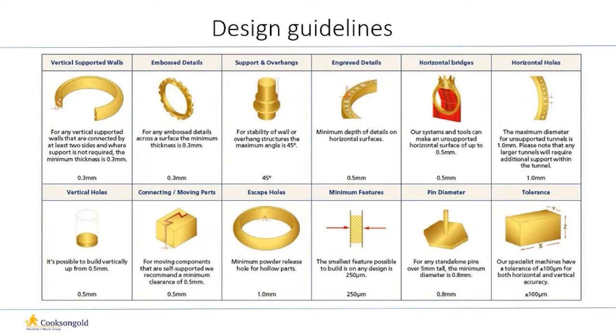Wall thickness that does not require supports needs to be 0.3 millimeters. For moving components that are self-supporting, we recommend a minimum clearance of 0.5 millimeters. For a hollow part, the release hole needs to be 1 millimeter. The smallest feature we can build is 250 microns.